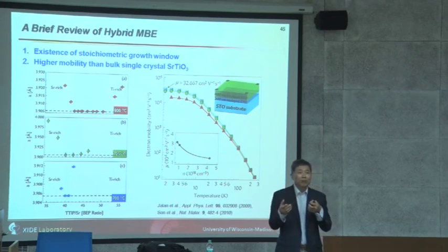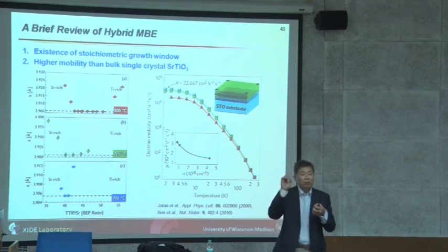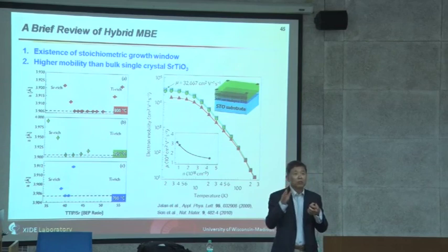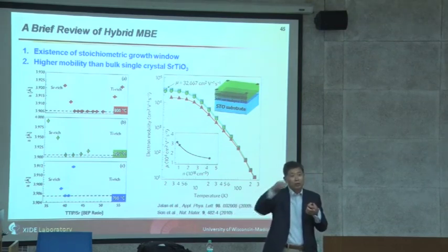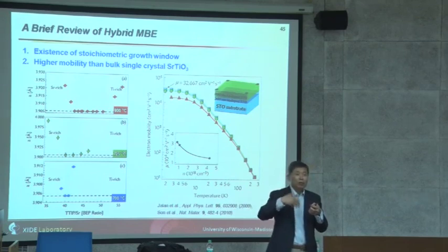Because when you do PLD, what we actually faced is a problem. I don't know what mode you do PLD in. Is it your energy constant mode or your voltage constant mode? You have two different modes of operation. In constant voltage mode, the energy drifts with time. Okay? Your laser energy drifts with time, which means your growth rate changes over time.